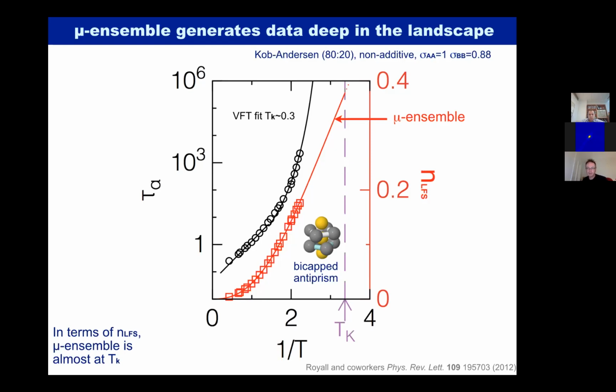What we can equilibrate in the simulations has maybe 18% of particles in the local structure. But with the mu ensemble, we can double that. And so it is as if we have gone to a much lower temperature, if we believe that the local structures are a measure of the temperature of the system. We have seen that the population of local structures increases as we drop the temperature, so we could presume that more local structures corresponds to a state at lower temperature than we can access in the computer simulation. And if it's at lower temperature, it should be slower and closer to the glass.